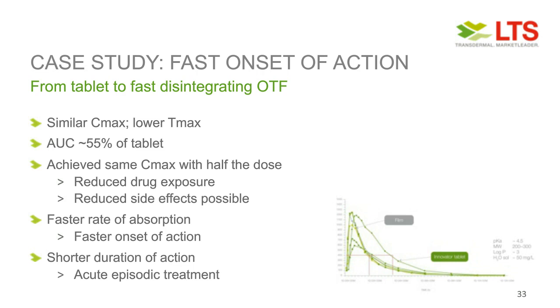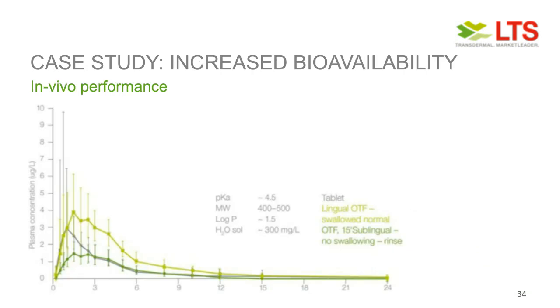The second example I would like to share with you is, as mentioned before, the increase of bioavailability. And here we see the plasma profiles, the curves, where we compare a tablet, already a commercial tablet, with two OTF formulations. The first one was just a lingual film with the same dose as the oral thin film. This is the light green curve. And it was just lingually applied and swallowed normally in this clinical setup. The second formulation had a reduced dose, only 30% of the tablet, and it was applied sublingually, but the subjects were not allowed to swallow for a certain time, which is pretty difficult to do, especially if you're told not to swallow. I think for patients this is pretty complicated, but in general you see where the trend is going.